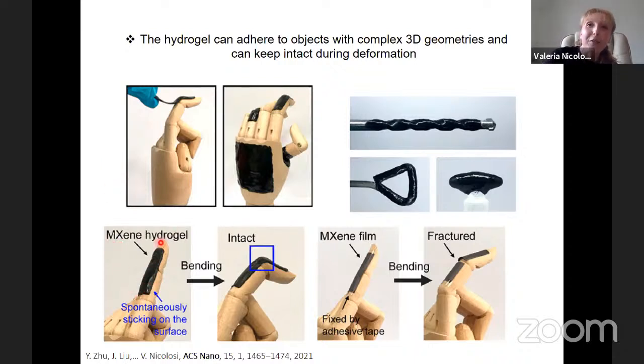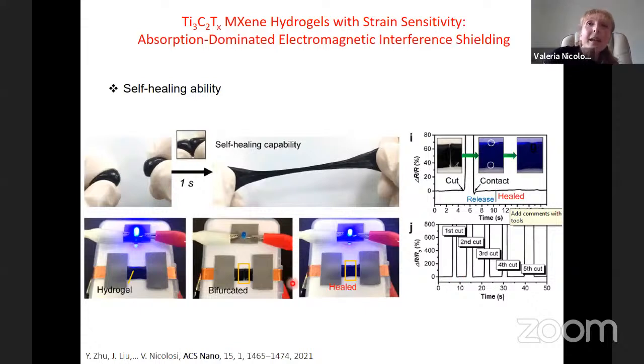Here is on a finger, and you can bend it, it's intact. If you fix it with adhesive tape, it's the adhesive tape that will break when you bend it. They are self-healable. Again, you can take it apart, you can put it aside, and after 1 second it is healed. And this is very nice because this is conductive, so you can make contacts and break contacts and then heal the contacts, and you can track that with electrical conductivity. You can light up the LED, switch off the LED, light up the LED when it's healed.